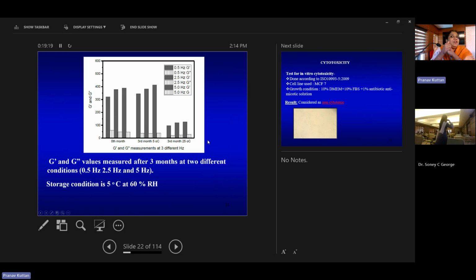So we generally, after developing a product, conduct stability evaluation, and there are lots of guidelines. ICH guidelines we follow actually. So as per that, at different temperatures and humidity conditions, because humidity plays an important role in the stability of a product, at a particular temperature and particular humidity, we will seal these products and we'll keep it in a shelf that is called stability chamber. It is actually an oven kind of a thing where you can monitor the temperature and the humidity, and you will store your products there. And at particular intervals of time, like 0th month, then 3rd month, then 6th month, 1 year, 2 year, you will withdraw certain number of products from that shelf, and you will evaluate.